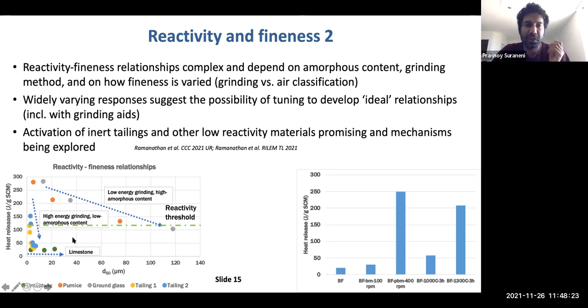But here the change is not just a change of fineness. The amorphous content is also changing. You can actually do XRD and find out which materials are getting amorphized. But the point here is that you get this different relationship for these materials, different from the relationship that you get for the high amorphous content materials and different from limestone. So you have a lot of different varying responses, which suggests the possibility of cleverly using chemical admixtures to tune these relationships, to develop some ideal relationships with some of these calcium aluminosilicate materials.